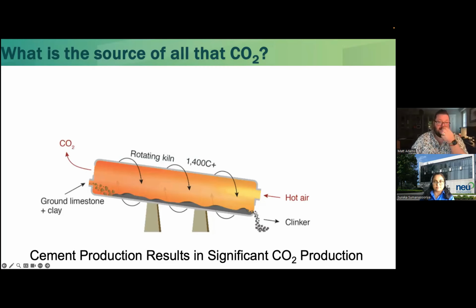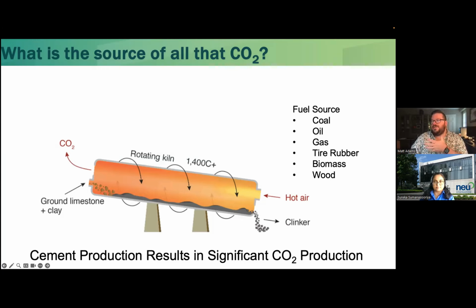So if you're familiar with cement production, we make cement in a large rotating kiln, and we heat that cement up to about 1400, 1500 degrees Celsius. And at the end, we get clinker that we crush down with gypsum to form Portland cement. During that process, we release quite a bit of CO2. First, like we said, about 40% is from the burning of the fuel source to heat the kiln. We've done a lot of work to make that more efficient, but at the end of the day, you're still burning quite a bit of fossil fuels.